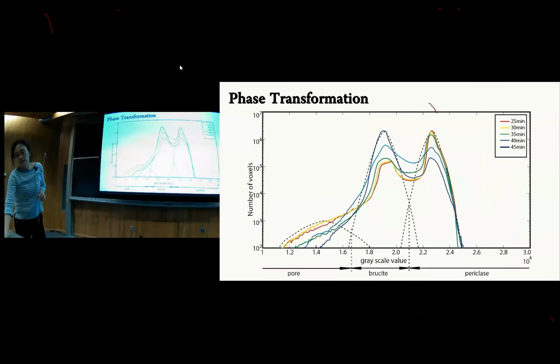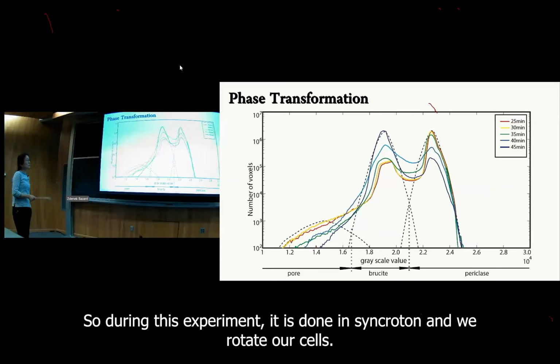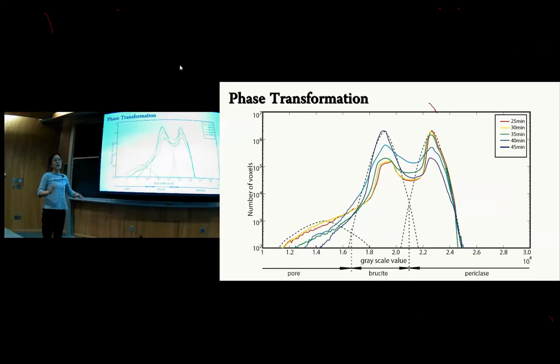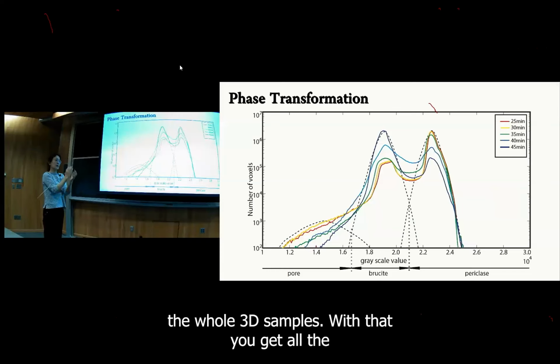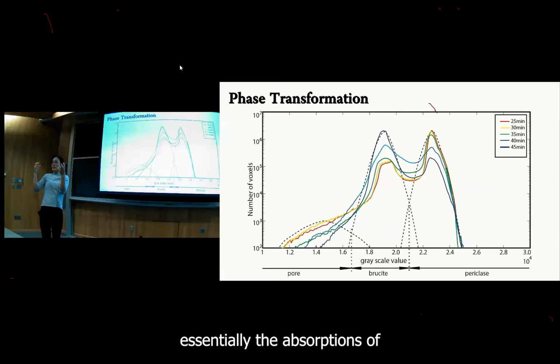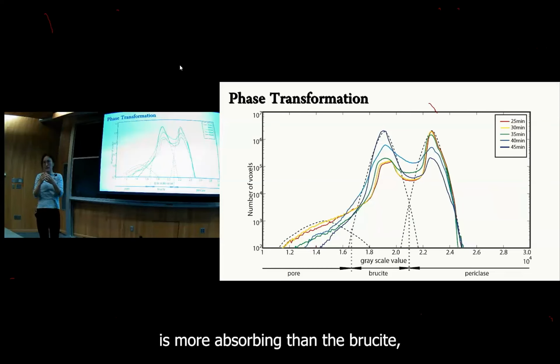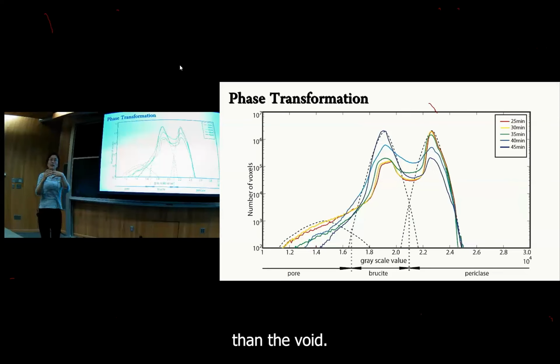And so one thing is, this experiment is done in a synchrotron, and we rotate our cells so you can collect 3D microtomography images of the whole 3D samples. With that, you get essentially the absorption of each mineral, because the periclase is more absorbing than the brucite, than the void.